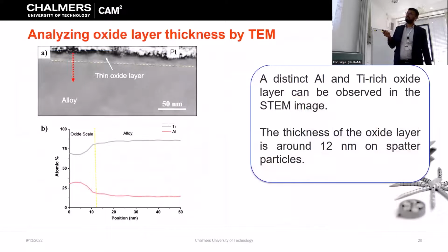To precisely measure the oxide layer thickness, we then did some TEM analysis. In TEM analysis, we can see that it is around 12 nanometers. And if we redo the adjustment of tantalum oxide with the etching rate of aluminum oxide and titanium oxide, we reach a similar value.